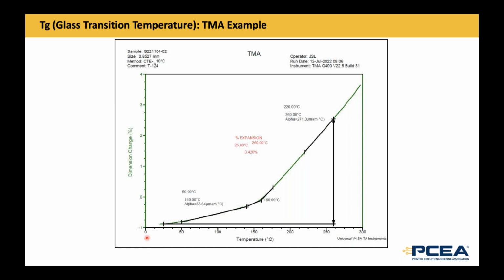It is one of the anomalies of this test. And in order to explain it, I would have to show you the entire thermal history of the sample. But suffice it to say that the zero position is set when you put the sample on the stage. A scan is done to relieve any stresses or remove moisture from the sample preparation. The sample is often prepared using a diamond saw with a wet process. And so the first scan is to settle the probe on the sample as part of the IPC procedure. And often the position of the zero moves down. If I could show this to anybody that wants to see what it actually looks like over the series, it's very common for the zero to go below the point that the probe sat at when you put the sample in the chamber.